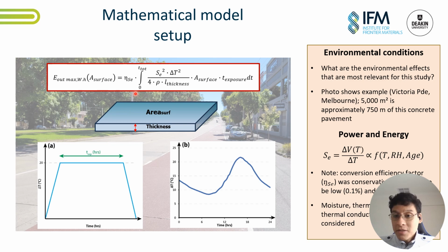The temperature regimes that we're using to evaluate the energy harvesting are two. The first one is a constant temperature gradient from 0 to 20 through 0 to 24 hours. This is most likely to be found in lab setups, but in real life, we don't have these temperature gradients. We have this one, which varies through time. So we have a minimum and maximum value.